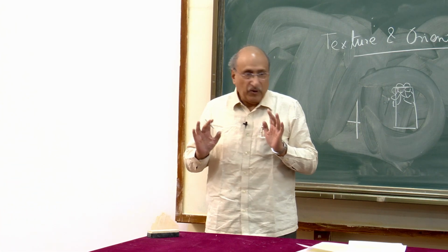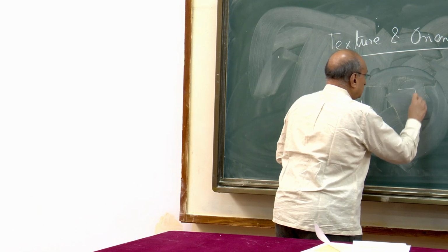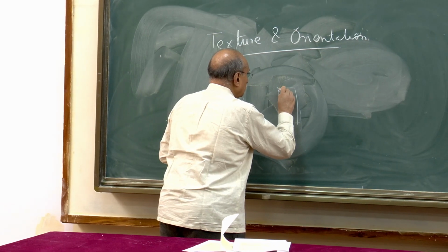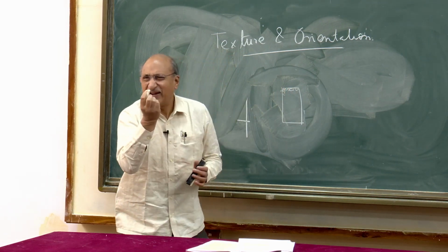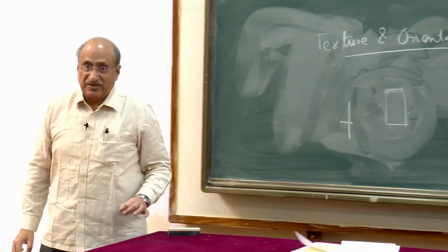You would rather have this grain size as small as possible, so that the part coming out of the bit becomes very small. If I have a very, very fine grain structure, then if one of them comes out, it will be a very tiny thing. So effectively the noise will be much lesser. That's why I'm interested in small size particles, small size grains. Because if I have to look at that application, I have to look at very, very small sizes.